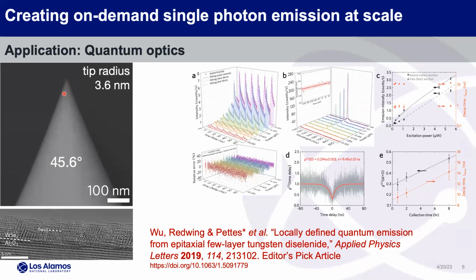You start with a big square, but it better be a square, a super square. It better be as square as you can make it. And then you just put it in hydrofluoric acid and it makes a super sharp tip. Then we put the 2D material on top of it. And what we see when we're looking at optical emission from the tip, and the measurements that I'm showing here, we did in Wright-Patterson, is that the emission coming from the tip is always in the 600 to 800 nanometer range and is very sharp.